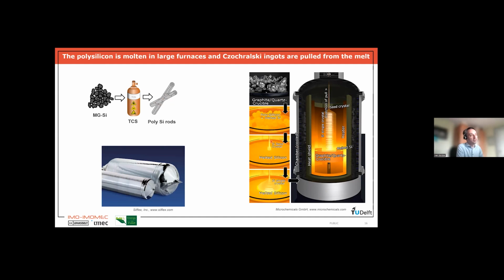And then we put just above this molten silicon a small silicon seed crystal. So this is actually a small silicon crystal that has a perfect crystallographic orientation. And by slowly pulling this silicon seed upwards, it actually pulls some of the molten silicon from the crucible with it. Once the silicon comes out of the crucible, it cools and it starts to solidify, crystallize, and it actually copies the crystal structure of the silicon seed. And this is a very slow process. So by doing this under the right conditions and slowly pulling the silicon seed crystal higher and higher, we actually pull a whole ingot, which can be a very large and heavy piece of monocrystalline silicon, out of this melt.